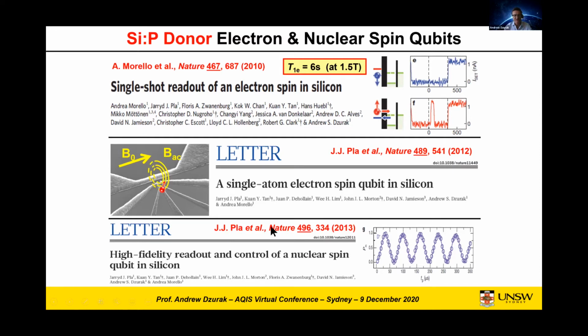Jarryd, Andrea, and our teams showed that it was possible to obtain very high fidelity control now of the nuclear spin. What you're seeing here are very high fidelity Rabi oscillations of the phosphorus-31 nuclear spin as originally envisaged by Bruce Kane. The way this is done is using an on-chip transmission line, designed using microwave engineering to deliver a reliable AC magnetic field. An AC current is passed through this line, producing an AC magnetic field around it, which is then used to rotate both the electron spin and the nuclear spin. This was designed to be broadband, so it could operate all the way from megahertz up to gigahertz.